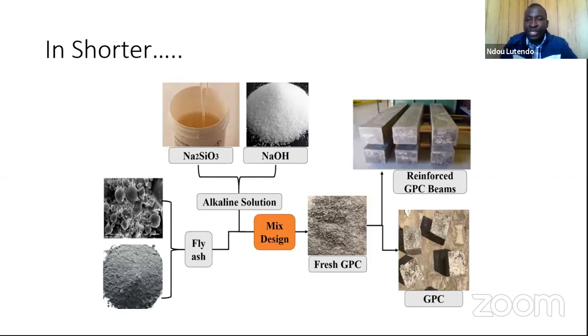And there are also some who are doing reinforced GPCs. You can see the GPCs are mostly used just to strengthen structures. In this case, you can see they use sodium silicate as an alkaline solution, and they also put sodium hydroxide there. Both of these are alkaline solutions, and they are mixed with fly ash. Now, what you see in this picture, I hope you can also see my cursor, is a picture that has been taken under SEM, scanning electron microscope. SEM takes a very close picture that shows you the crystalline structure of a material. In geology, that's what we call the morphology. That's what we zoom in to see. And when you have mixed the solution and the fly ash, you have fresh GPC that can be molded and cast, and then you can form a very nice strength for your building.